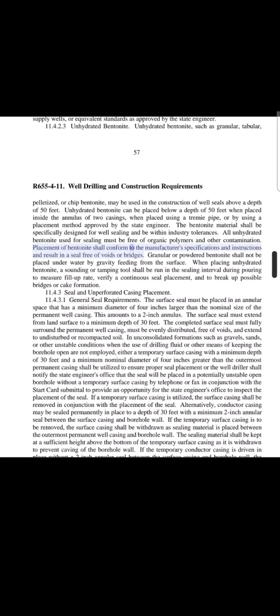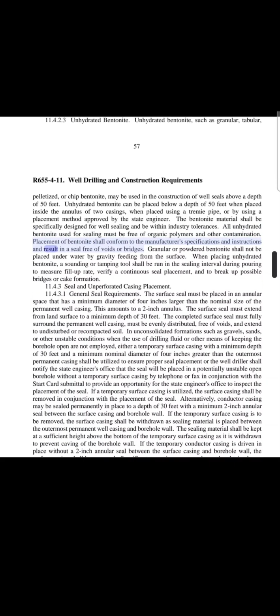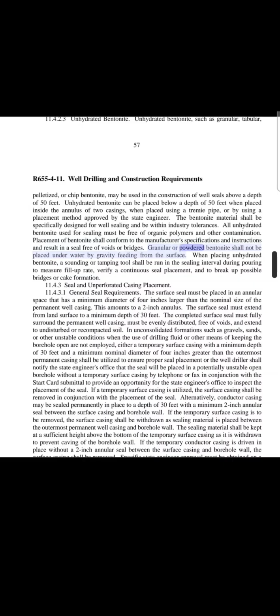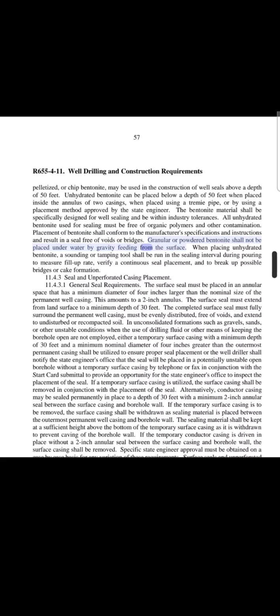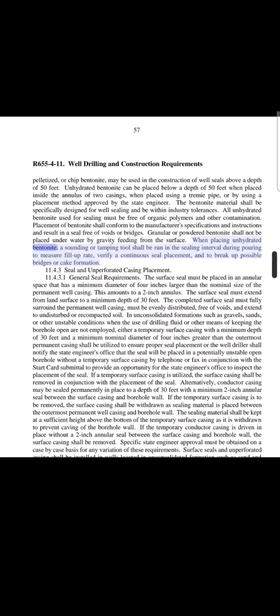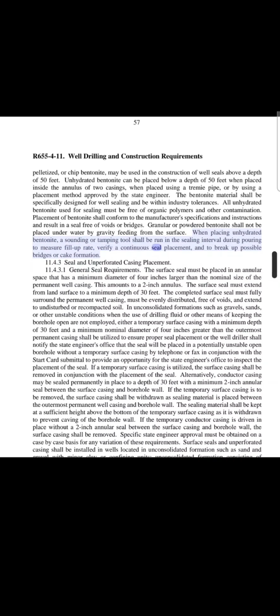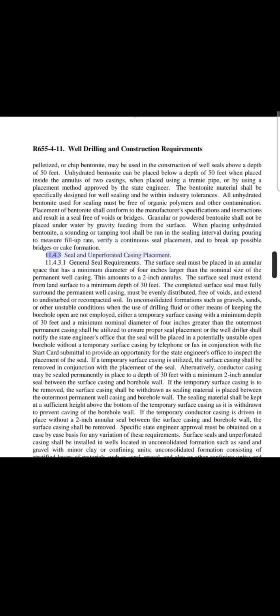Placement of bentonite shall conform to the manufacturer's specifications and instructions, and result in a seal free of voids or bridges. Granular or powdered bentonite shall not be placed under water by gravity feeding from the surface. When placing unhydrated bentonite, a sounding or tamping tool shall be run in the sealing interval during pouring, to measure fill-up rate, verify a continuous seal placement, and to break up possible bridges or cake formation.